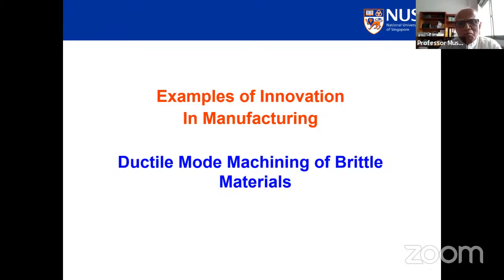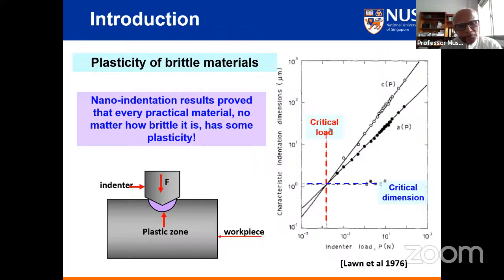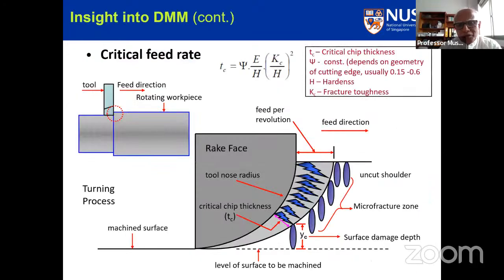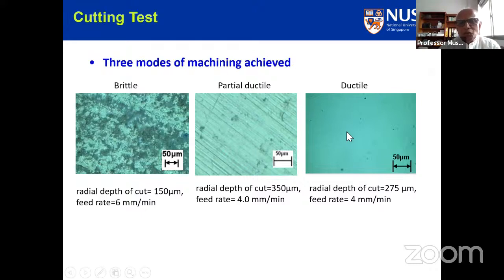And because of this machine, we even dared to do ductile mode machining of brittle material, which I will not go into in detail. We tried silicon, where a nano indentation test proved that after depressing the indenter more than one micron, it cracks. So using that 1 micron as a critical chip thickness, we carried out up milling. As chip thickness goes to 1 micron, it will crack. So we subdivided this, less than 1 micron, into hundreds and thousands of divisions. Because the machine is absolutely accurate, we have been able to do ductile mode machining of brittle material.